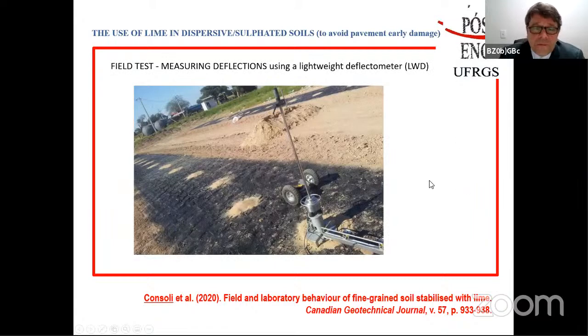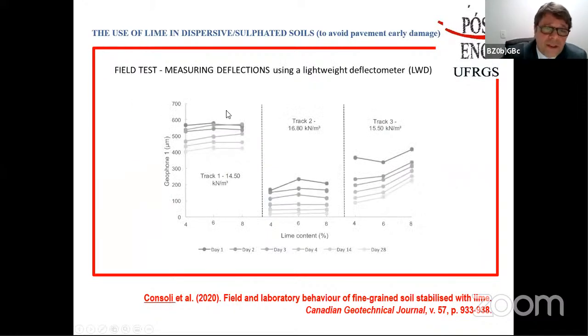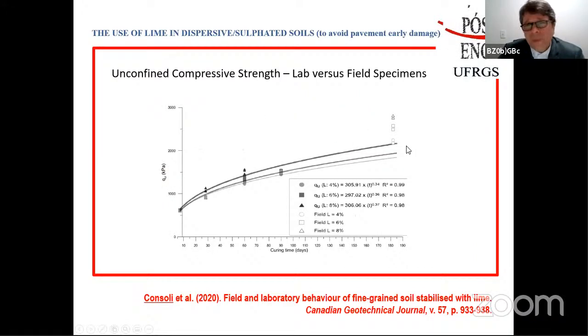As for the results of this study, here we have the lightweight deflectometer to check the stiffness that we get over time. And here we have the results. For example, with denser compaction, we get higher dry unit weights through that energy, and with different amounts of lime, we show that working between 4 and 8% of lime didn't change the results so much. But of course, with time, the stiffness increases due to the cementitious reactions, the cement working, the hydrates, and also the pozzolanic reactions between the lime and the soil, and then you greatly reduce the deflections with time. So this is after 1 day, and this is after 28 days of curing. You can find this in the Canadian Geotechnical Journal. The reference is below here.